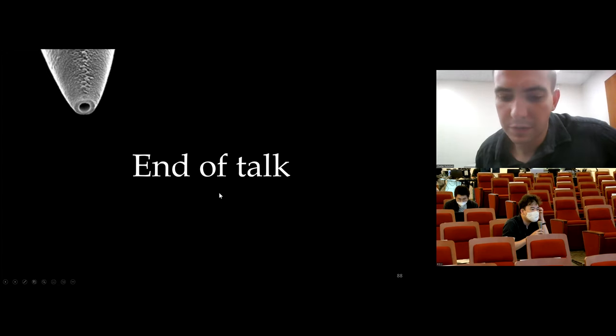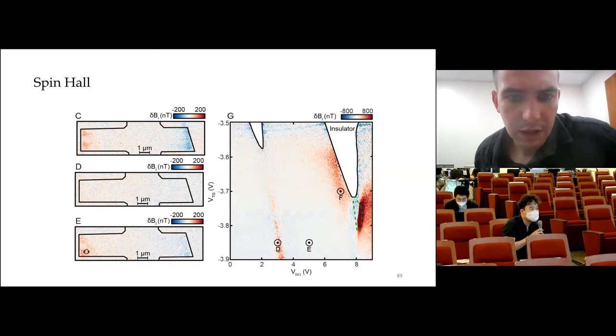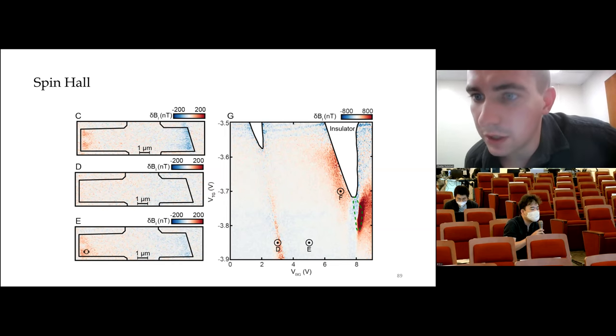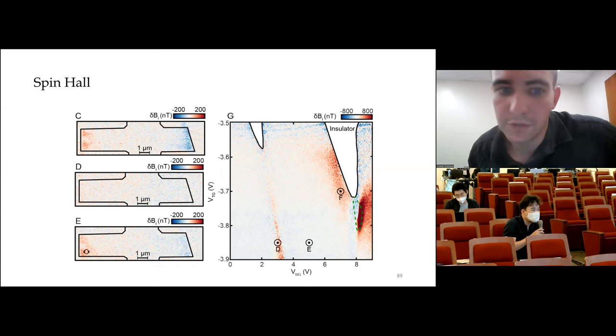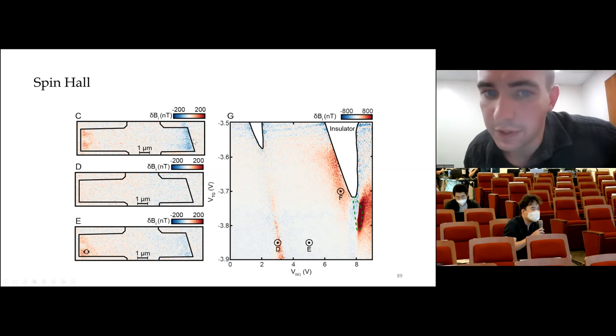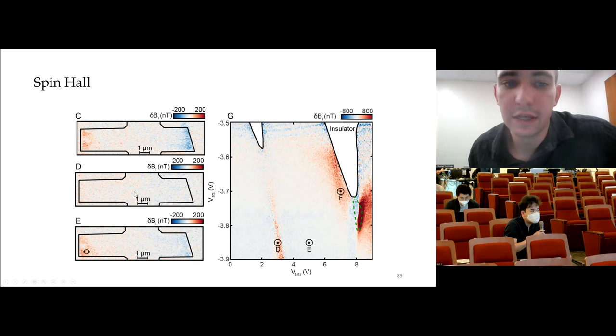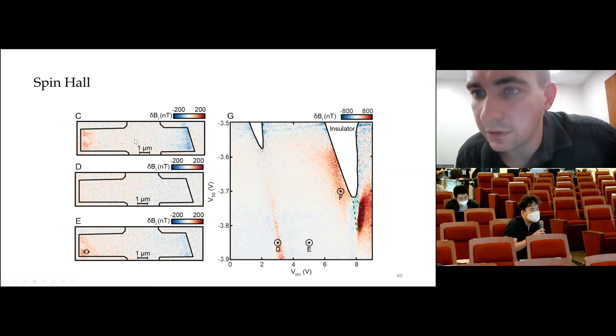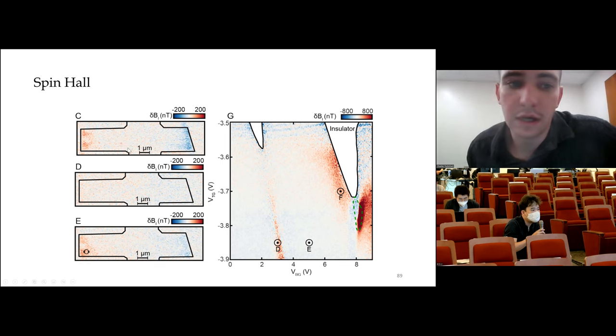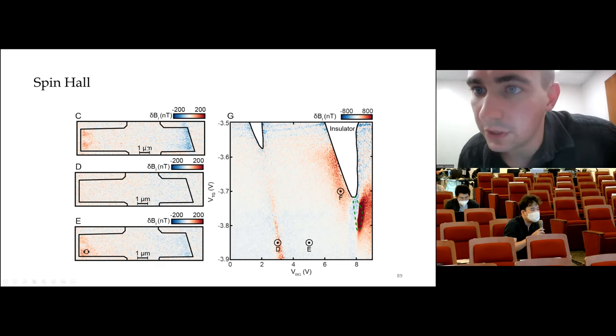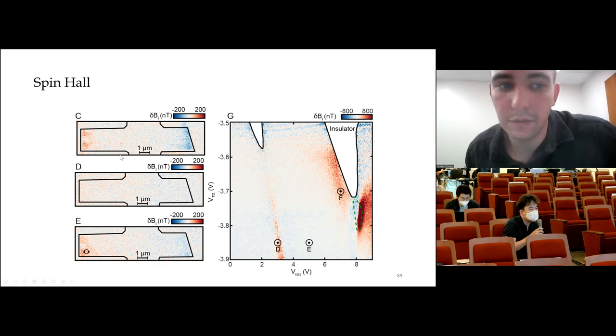A piece of information that we have that I didn't put in the talk is that we can image the spin Hall effect in this system outside the quantum anomalous Hall regime. What you're seeing here is a 2D scan of the same region showing local magnetic field associated with an AC current. To be clear, AC currents will generate magnetic field from the Biot-Savart law, but much smaller than we would be sensitive to here. So any local magnetic field is associated with spin accumulation.